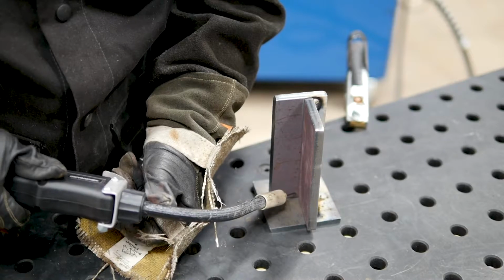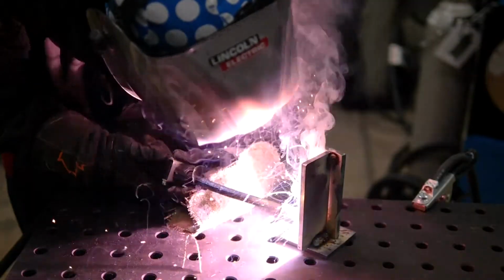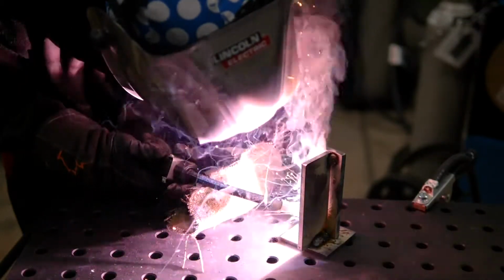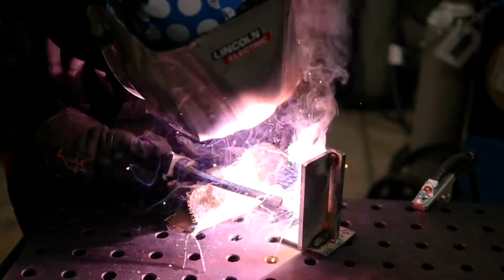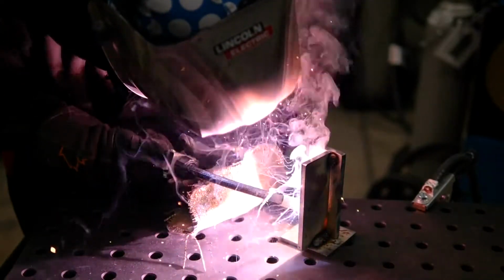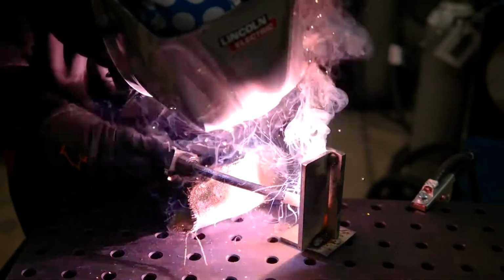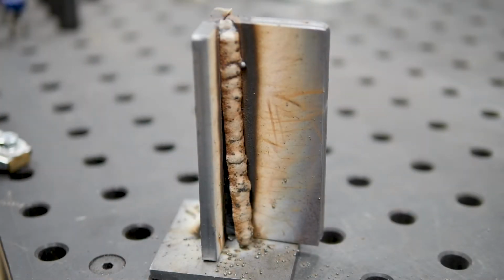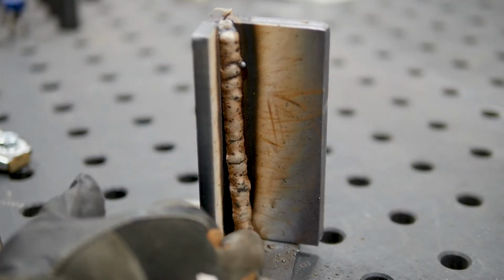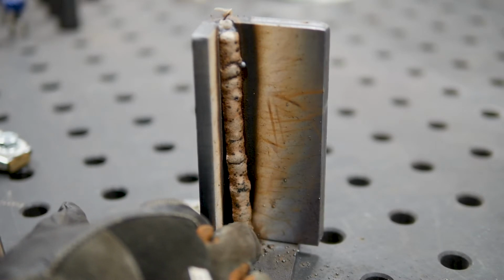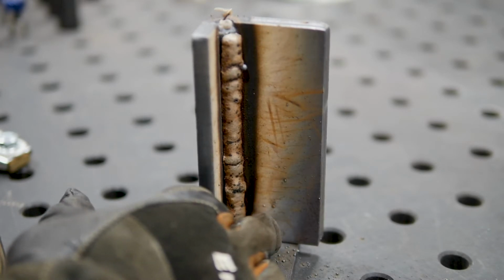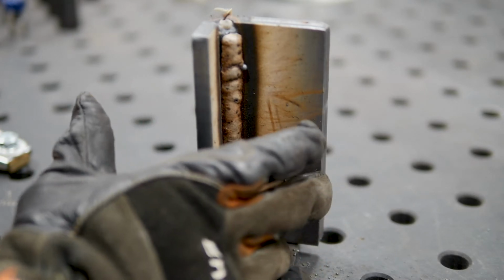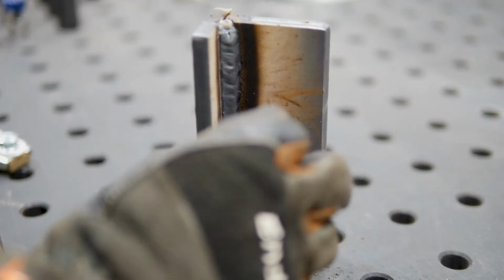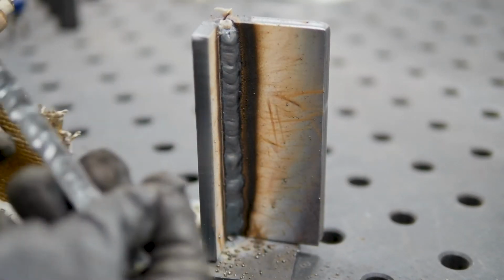So you want about a 10 to 15 degree downward angle, and then we'll weld up and we'll build ourselves a little slag shelf, and we'll ride that slag shelf all the way to the top. One of the ways that you know that you did a good job when you're welding with this wire is that the flux will just start to peel off on its own. That means you maintained that good downward angle and the flux floated to the surface. Now we're just going to pull this off, a little warm. Look at that, it's just one solid piece of flux.